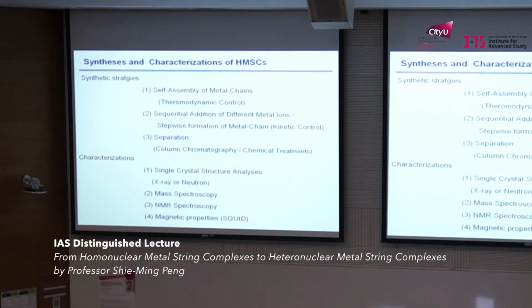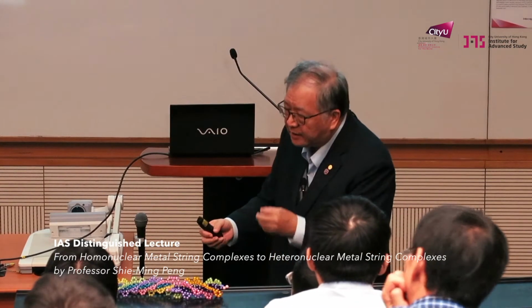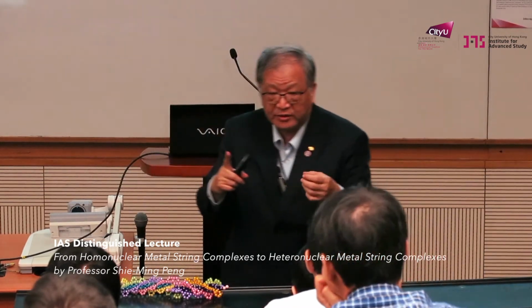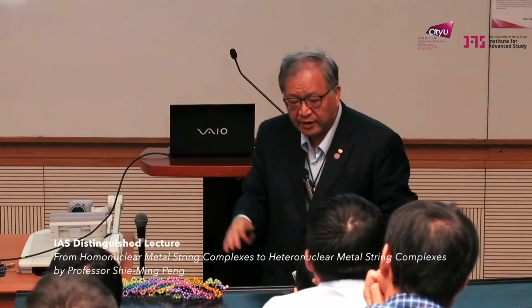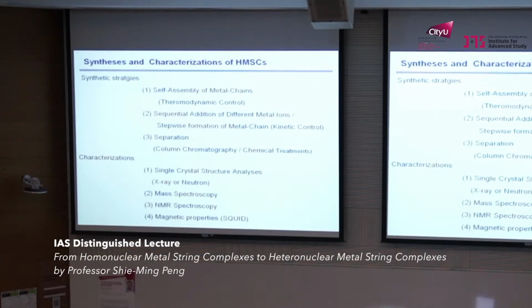Or even in the worst case, you have so many compounds, some of them you can use a column to separate the isomers. And for characterization, mass is also diagnostic, because many transition metals have isotopes, or paramagnetic NMR, or single crystal, which now faces a problem because you have the heteronuclear one. X-ray cannot differentiate nickel and cobalt because they only differ by 1 electron in electron density. So in the same row, it is difficult to characterize them by X-ray diffraction. But now we try to use neutron diffraction, okay? Because the nuclear cross-sections for nickel and cobalt are completely different.